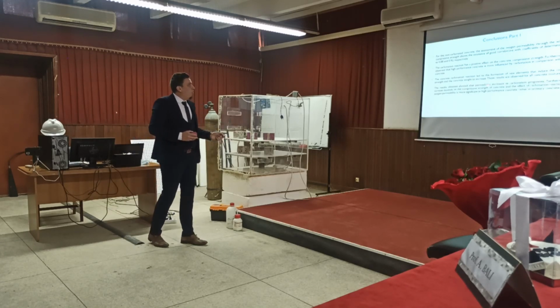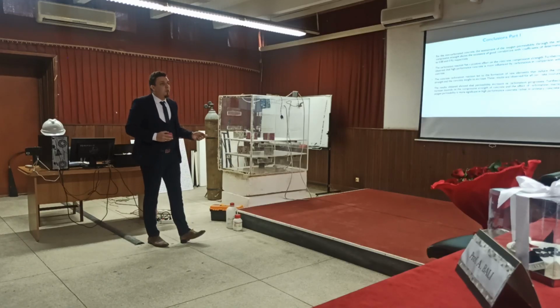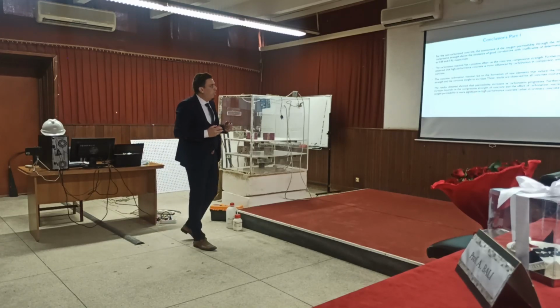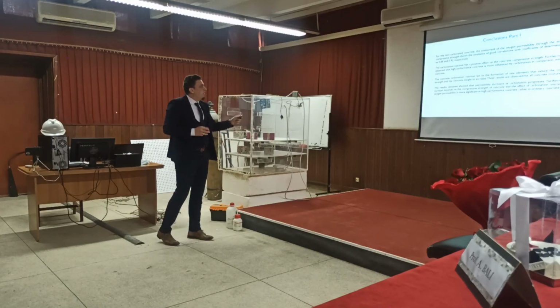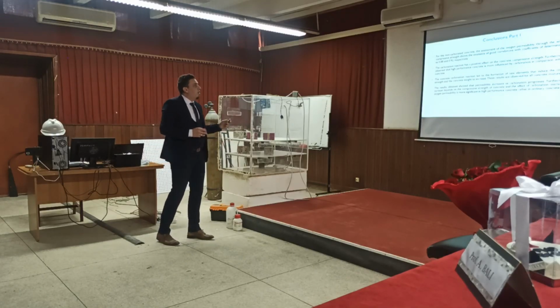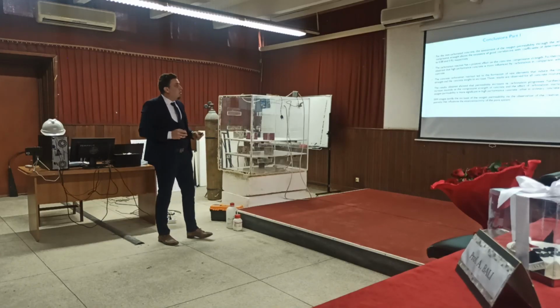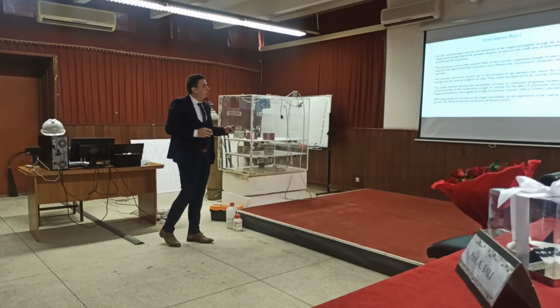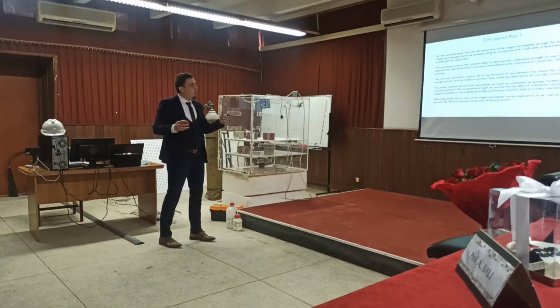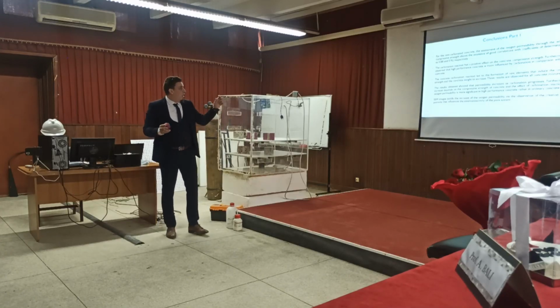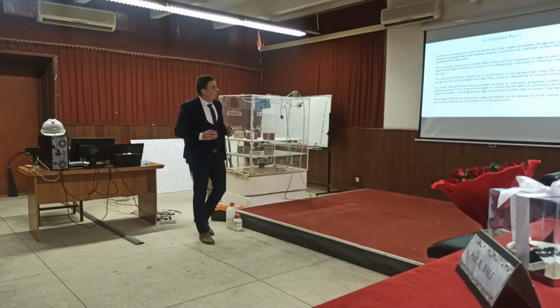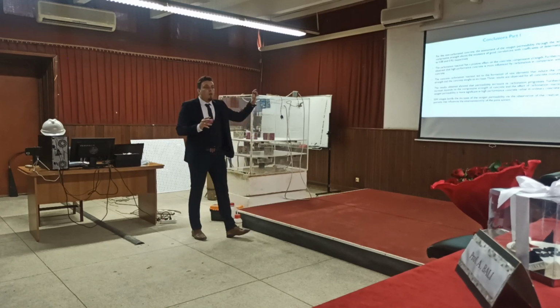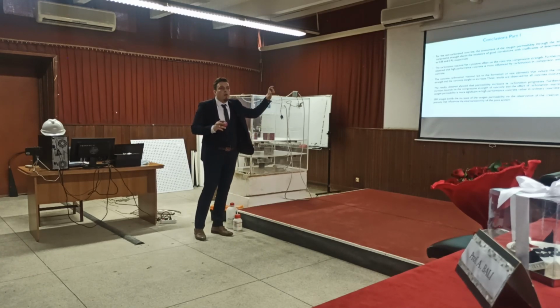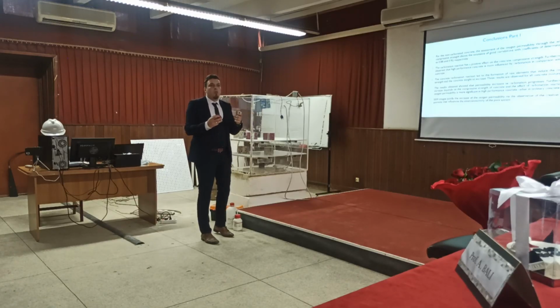The results obtained show that permeability increases as carbonation progresses. Furthermore, this increase depends on the compressive strength of concrete, and the effect of the carbonation reaction on the oxygen permeability is more significant in high performance concrete than in ordinary concrete. Some images justify the increase of the oxygen permeability via the observation of the creation of larger pores that influence the interconnectivity of the pore system. Now, arriving at the conclusions of part 1, we can enter the second part with confidence.